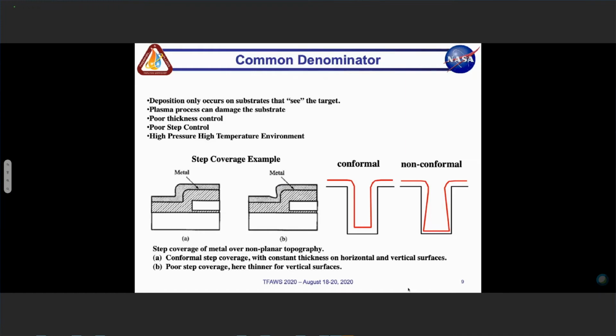So here is an example of what step coverage looks like. If you have a 90-degree type of step, what you want is a very conformal material that wraps around that step. But what you end up seeing is a material which is not conformal. So you end up with grooves and not a uniform thickness. Talk about conformal and non-conformal types of coatings.